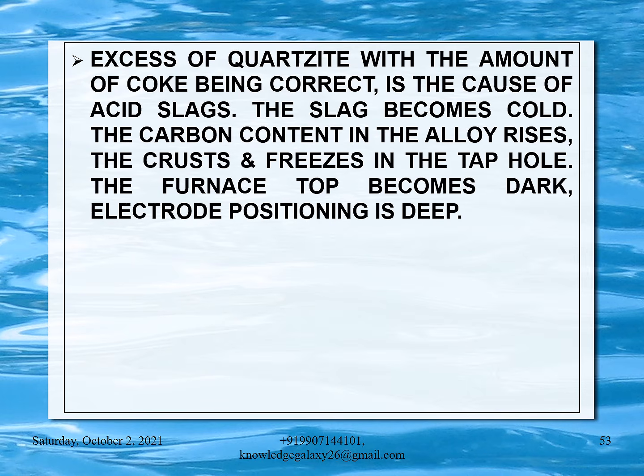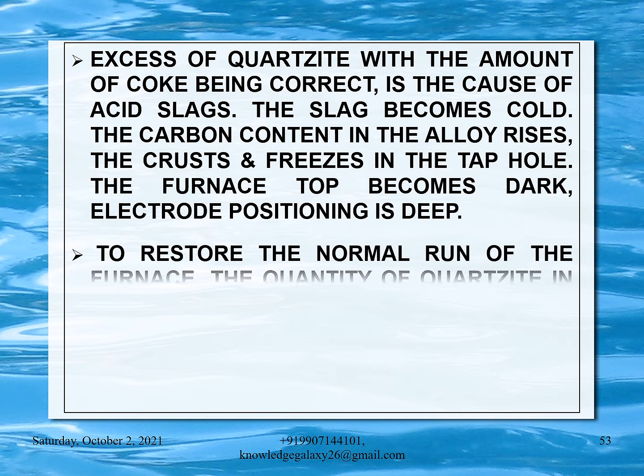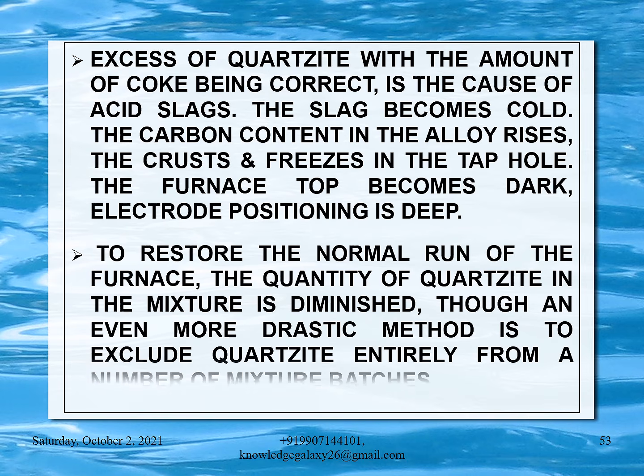The other problem is excess of quartzite with the amount of coke being correct, which is the cause of acid slags. The slag becomes cold, the carbon content in the alloy rises, the crusts and freezes in the tap hole, the furnace top becomes dark, electrode positioning is deep. To restore the normal run of the furnace, the quantity of quartzite in the mixture is diminished, though an even more drastic method is to exclude quartzite entirely from a number of mixture batches.